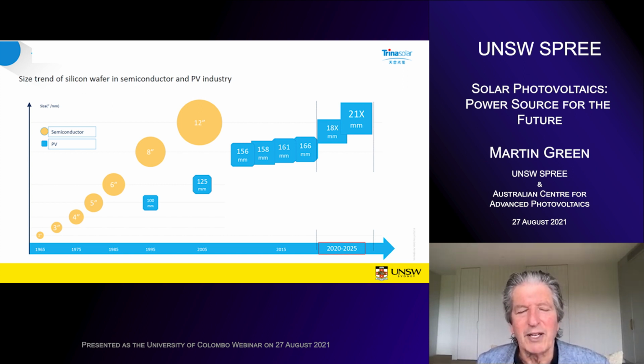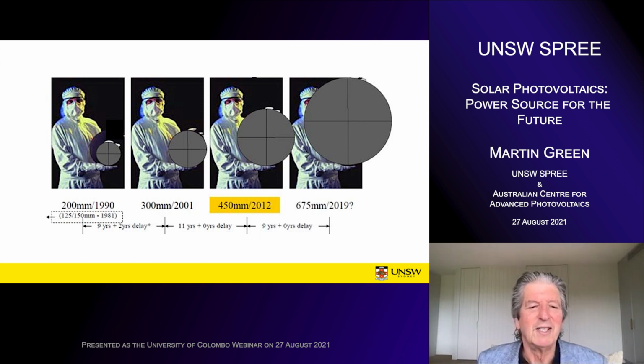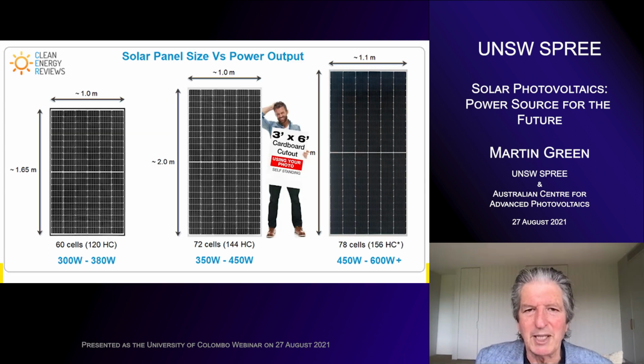But now you can cut the wafers into smaller cells. You can go to bigger wafers. So now the industry is going to the biggest square wafer you can cut out of a 300 millimeter diameter wafer. And we might even get ahead of microelectronics in going to bigger and bigger silicon crystals, because microelectronics is hampered by the processing requirements, particularly making very fine line widths on these wafers, which is not required for photovoltaics. Microelectronics had a roadmap where they would go to bigger and bigger wafers over time, but the challenges of doing fine line width lithography on these big wafers have held back the progression to even bigger wafers. But in photovoltaics, we may be able to do that.